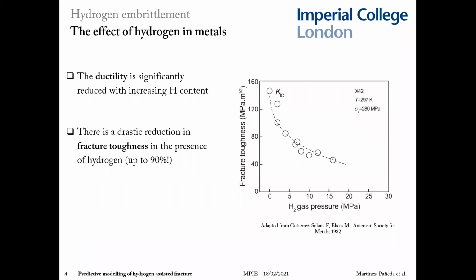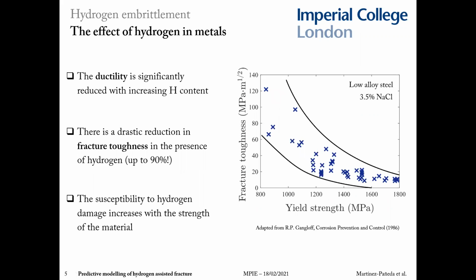Another important effect is the drastic reduction in fracture resistance. You can see in the slide that with increasing hydrogen content, we go from a fracture toughness of roughly 150 megapascals square root meter to a fracture toughness that easily goes below 40 megapascals square root meter. And this is a low strength steel. In high strength steels, the reduction in fracture resistance can be of up to 90%. And this is a very important point to emphasize. The susceptibility to hydrogen damage increases with the strength of the steel.